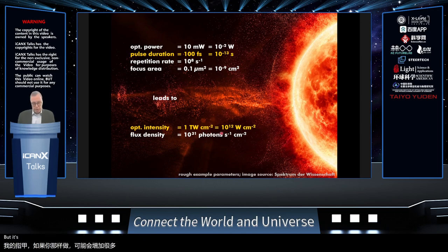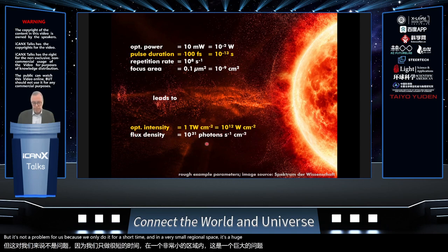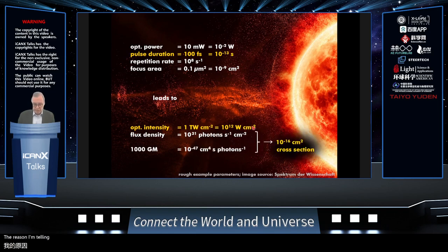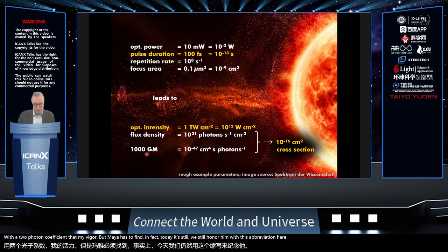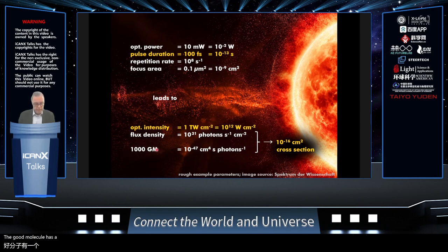But it's not a problem for us because we only do it for a short time and in a very small region of space. It's a huge number of photons per second and per area. And the reason I'm telling you this is because you can now take this number and multiply it with a two photon coefficient that Maria Goeppert-Mayer has defined. In fact, today we still honor her with this abbreviation, GM, the unit for Goeppert-Mayer. A good molecule has a coefficient of 1,000 Göppert-Meyer, and that would be this number here.